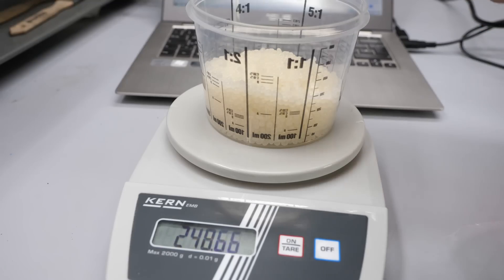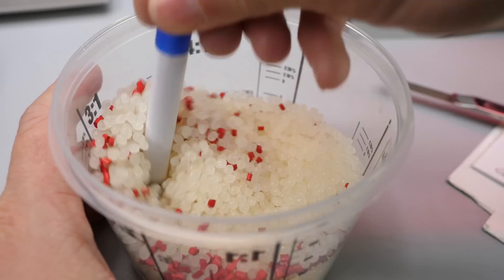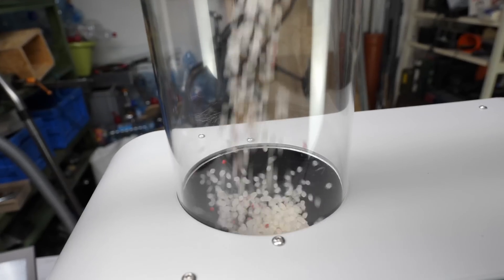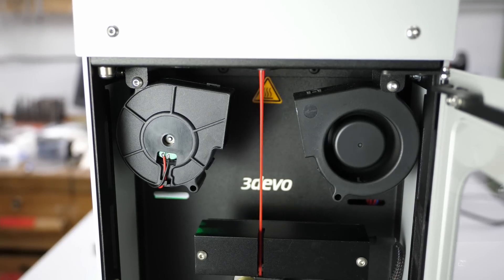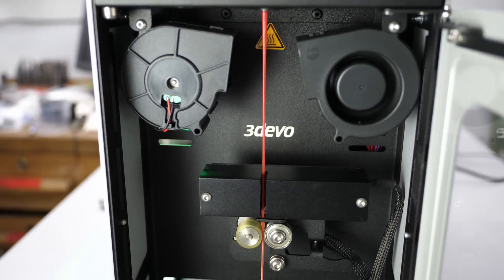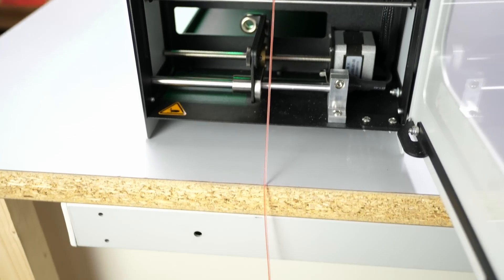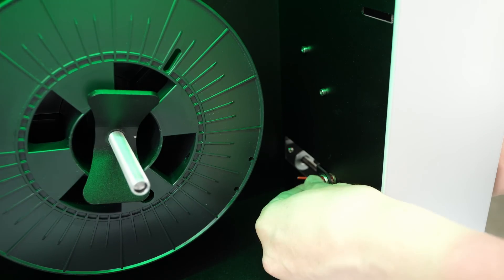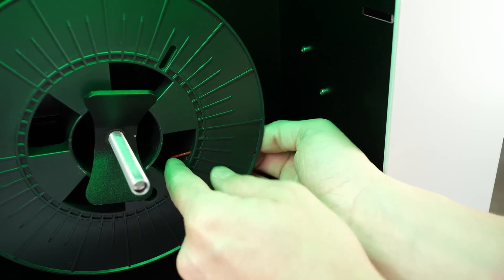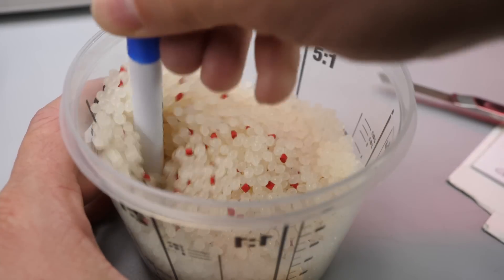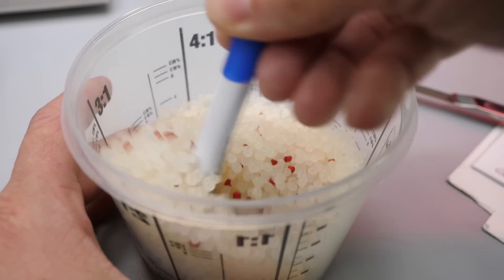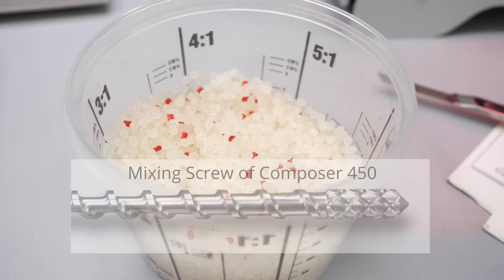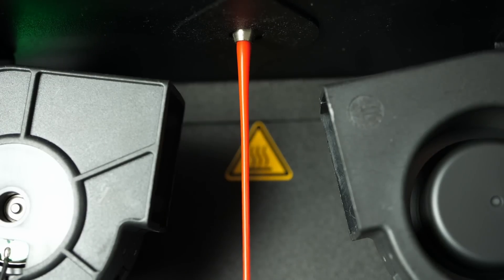Let's first start with red filament. For that, I add 2% of masterbatch to my PLA pellets, thoroughly mix it and fill everything into the hopper. Of course, it again needs a couple of minutes until we get red material out of the nozzle because we have to purge out the old material at first. After that, it's the same procedure as before, threading the end of the filament through the positioner and the spool and start winding. Since there aren't many particles of masterbatch in the pellets, it's very important that the extruder screw builds up pressure and performs a lot of mixing and shearing motion in the metering zone to mix the melt properly and to get even colors.